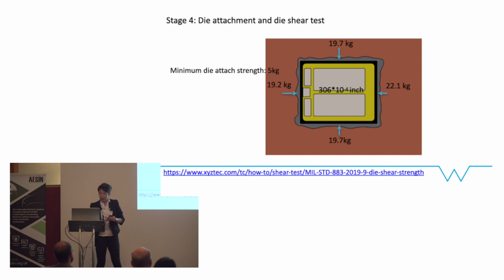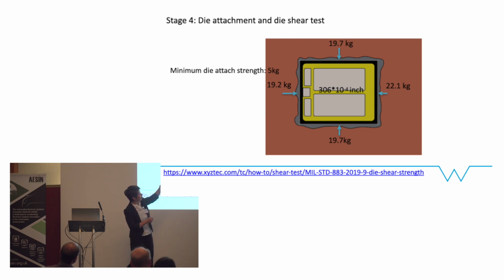And then after the die attachment, you need to do a shear test to make sure it meets the minimal shear requirements. Based on the size of the die, the minimal die attach strength should be at least 5 kilograms. And what we did is a destructive shear test in 4 different directions of the die. And fortunately, they all passed the requirements, you can see. They are all much higher than 5 kilograms.